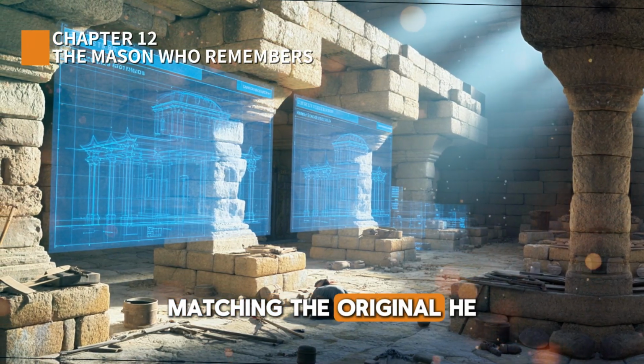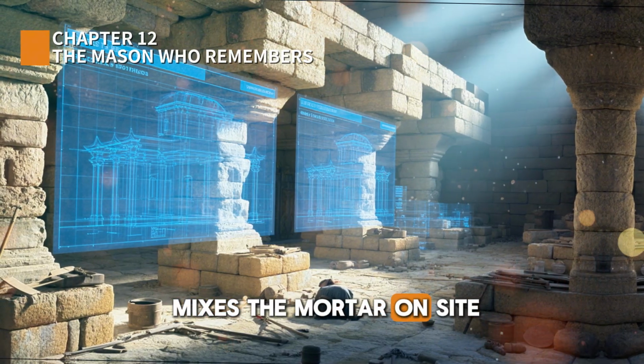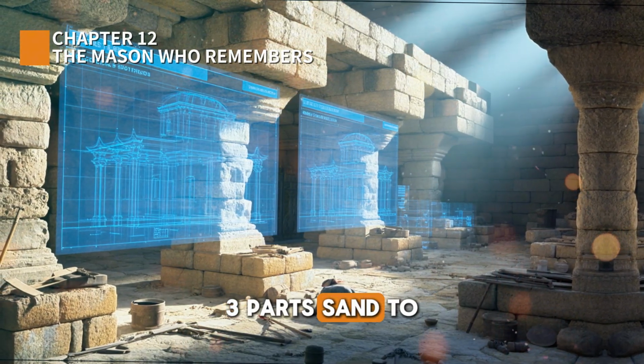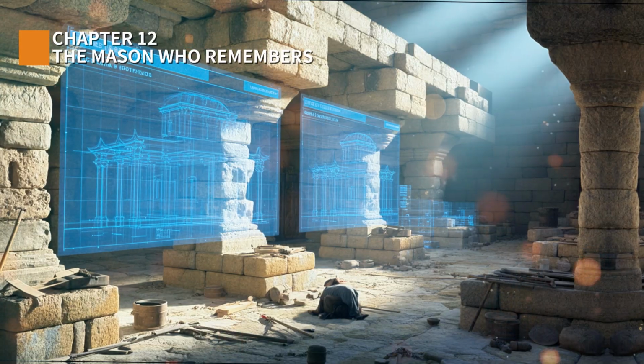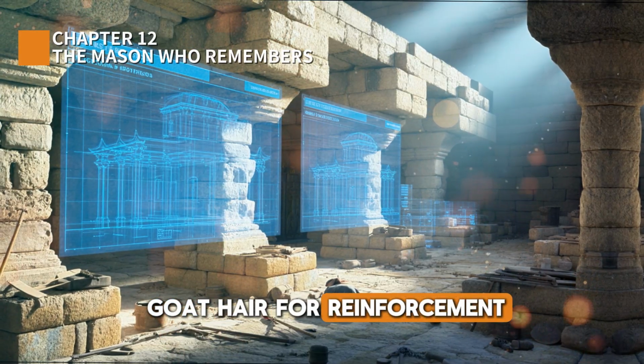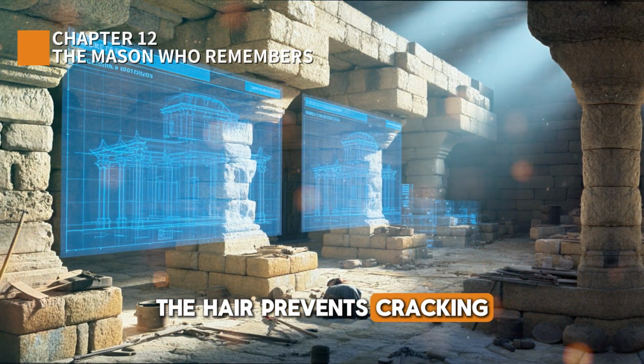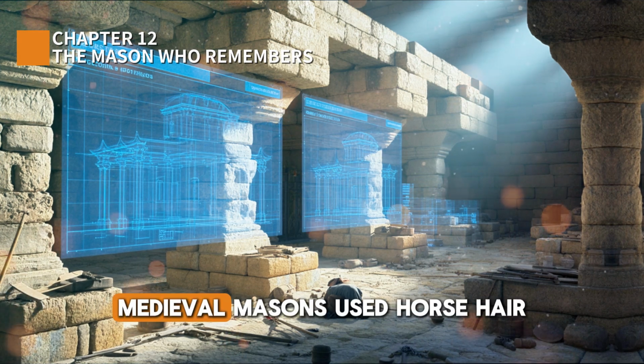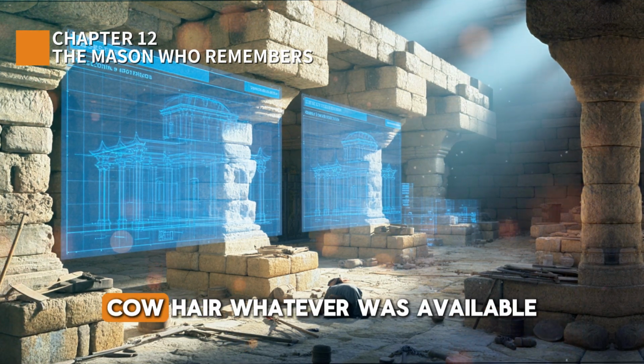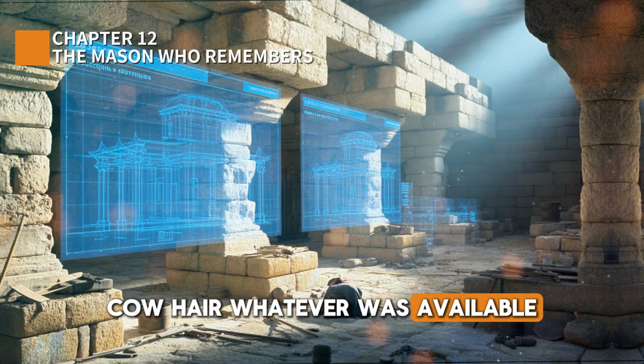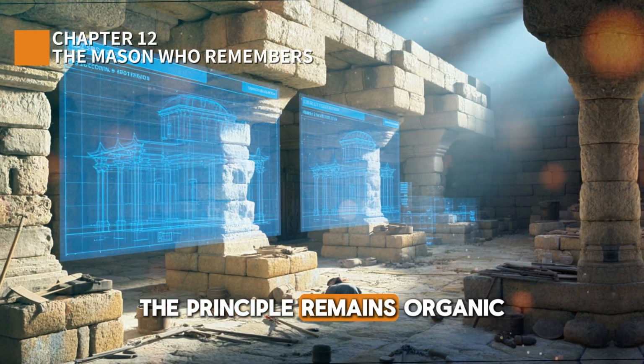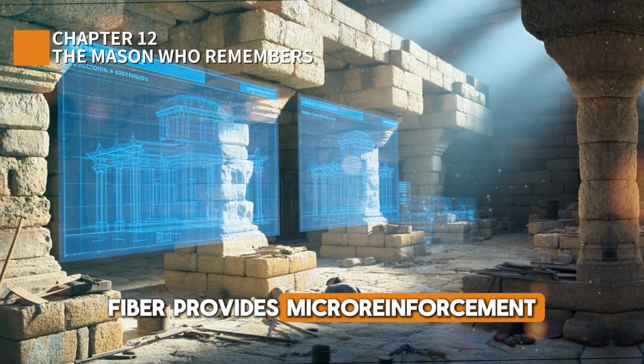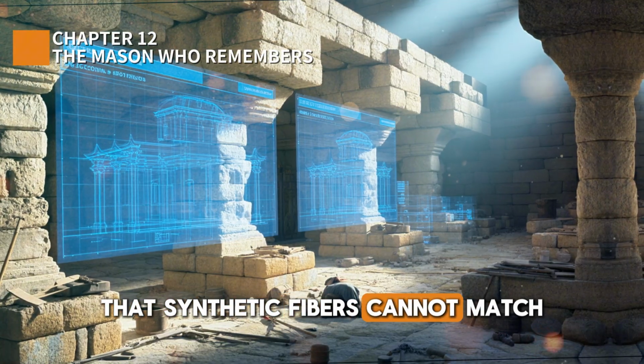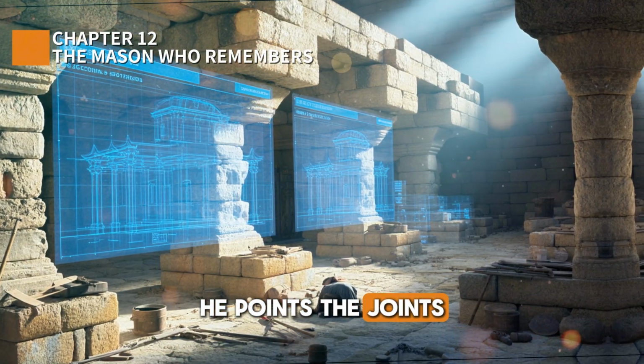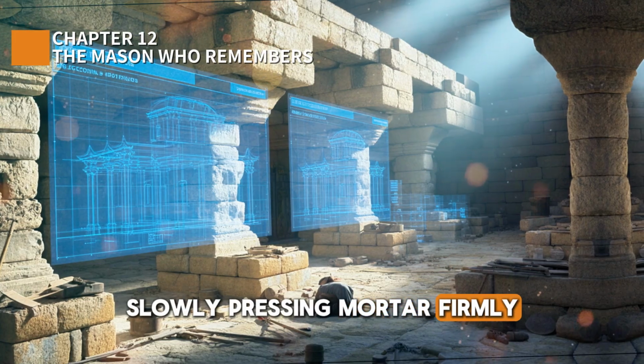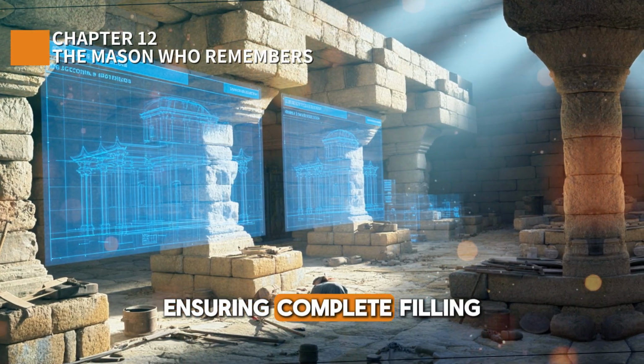He mixes the mortar on site. 3 parts sand to 1 part lime, plus a handful of goat hair for reinforcement. The hair prevents cracking as mortar dries. Medieval masons used horsehair, cow hair, whatever was available. The principle remains: organic fiber provides micro-reinforcement that synthetic fibers cannot match. He points the joints slowly, pressing mortar firmly into voids, ensuring complete filling.